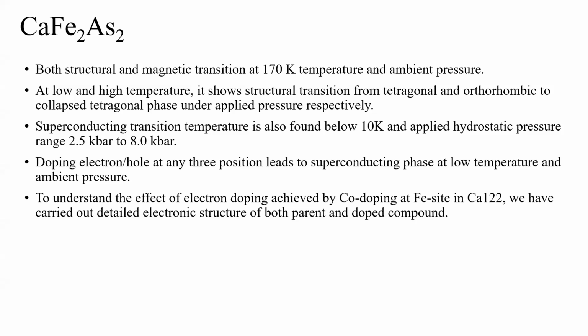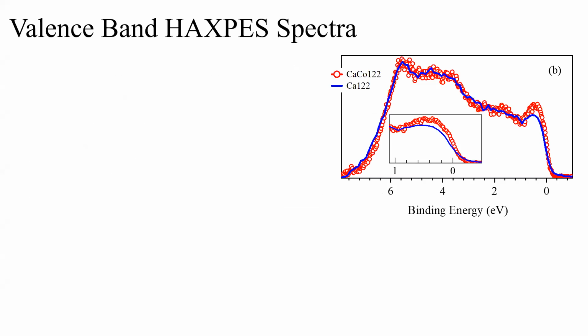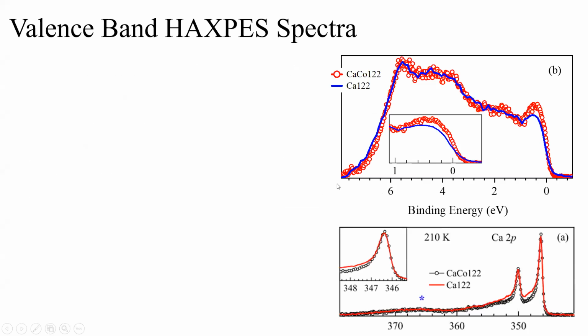We just wanted to see what kind of changes this electron doping at the iron site can give in the electronic structure of the compound. So for that, we studied the electronic structure of both the parent and the cobalt doped compound. First, we looked at the angle integrated photoemission spectra in the valence band region using hard X-ray photoemission spectroscopy. The open circles are from the CaCo122 compound, and the lines represent the Ca122 compound. Ca122 is CaFe2As2 and CaCo122 is cobalt doped CaFe2As2.